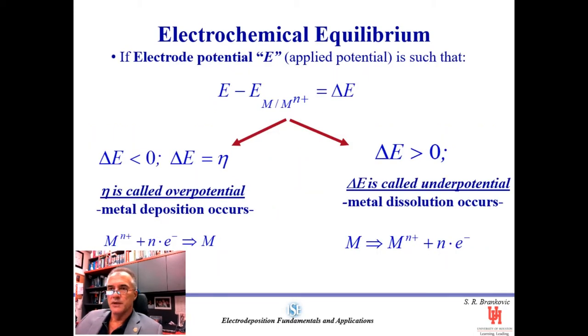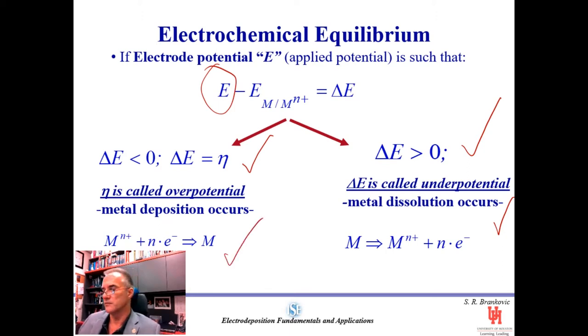So we have to appreciate the fact that application of potential to the electrode surface could drive one of these two reactions to become the dominant one. If the applied potential E is such that the net difference between equilibrium and applied potential is positive, then we are talking about conditions of underpotential and the metal dissolution reaction is favored. However, if the applied potential is such that the difference between applied and equilibrium potential is negative, then we are talking about eta, which is the common denomination for overpotential, and the electrode at these potential conditions favors the reaction of metal deposition, or metal ion reduction.